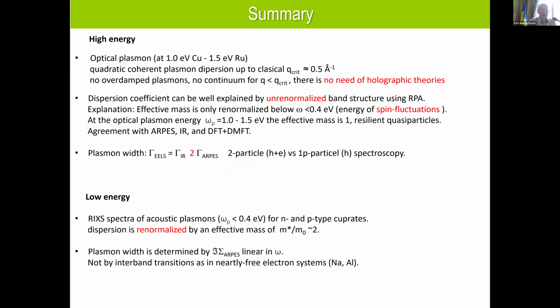So this is then the summary. For the optical plasmons, we see plasmon at an energy of 1 eV or 1.5 eV for the ruthenates. We see quadratic coherent plasmon dispersion, which decays when we move with the plasmon dispersion into the continuum. We see no overdamped plasmons below this continuum, this Lindhard continuum. So there, from our side, there is no need for holographic theories which predict overdamped plasmons.